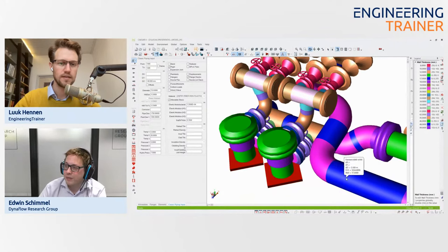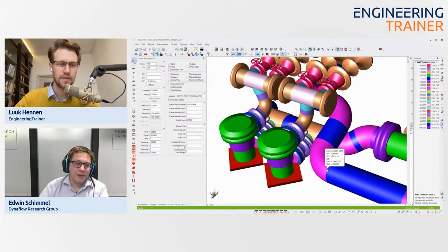And that is that, for example, if the stress in this area is high, then we can just apply additional thickness by laminating on this stretch of piping. Yeah? So we saw a previous picture where we saw the laminated joint, where they apply the woven and wind it around the pipe. Right. But you can do it at joints, but also on just a straight pipe. So by doing that, you increase the wall thickness. Could be practical to make the same thickness as the elbow, for example. And yeah, it's a simple logic that with a higher wall thickness, the stresses reduce.